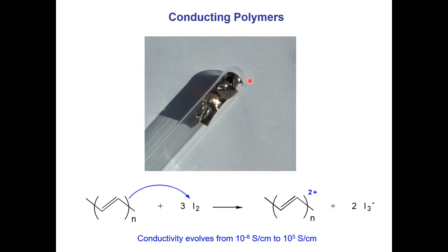And this material was able to transport current very, very efficiently. Actually, then we realized that what this student did was to make a redox reaction between the polymer and redox agents. And by removing electrons from the polymer, well, the polymer chains became electrically conducting. And the conductivity was boosted from a very, very small value in the pristine, the initial state, to a very large electrical conductivity, similar to copper, a very good metal, by this kind of chemical doping.